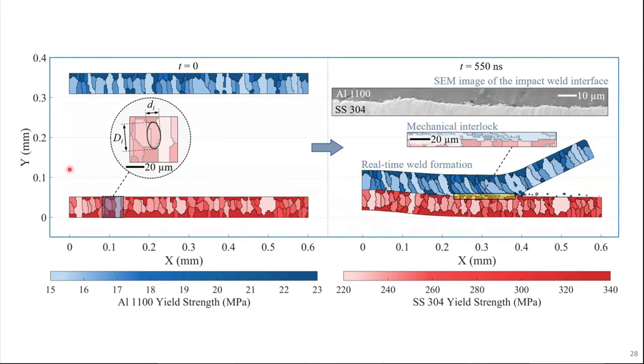The first picture you see on the left is at a frame T0, which means before the laser pulse is applied. And then T equals 550 on the right means well into the laser impact weld formation. You see all that jetting on the side. And if we zoom in to the interface, we notice this sort of mechanical interlock that we're predicting. Just to compare, I've also attached an SEM image. Now, this SEM image, I will note, is not from an additively manufactured foil, but you should still get the interlocking. It may not be exactly the same, but just to give you an idea, if you notice the interface, you see that interlocking phenomenon occurring.